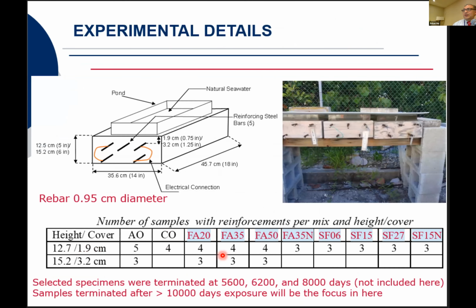These are the geometry of the samples and an old picture of the samples. You can see that most of the samples have 1.9 centimeters of concrete cover, or 3/4 of an inch. A few of them had 1.25 inches of concrete cover, or 3.2 centimeters. Most of the samples that I'm going to be describing today had a concrete cover of 1.9. Over the years, we have terminated samples. We terminated some after about 5,600 days, others after 6,200 days.